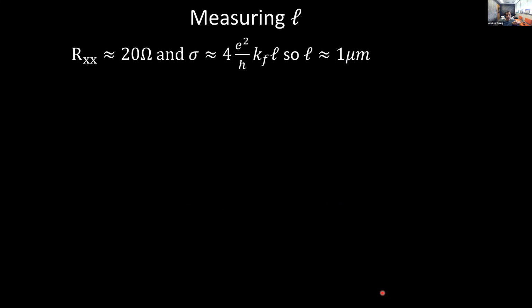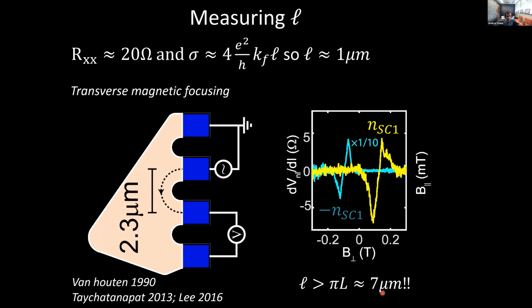Okay. As far as L, the mean free path, we can think about what the normal state resistance is and its density. So that simple estimate gives you something on the order of a micron, which is already considerably larger than the estimated coherence length. But actually, there's a much more stark measurement that you can do given this device. So this is actually what the device looks like. It's sort of cut out in a funny triangular shape, but it has 4 contacts all along one side.